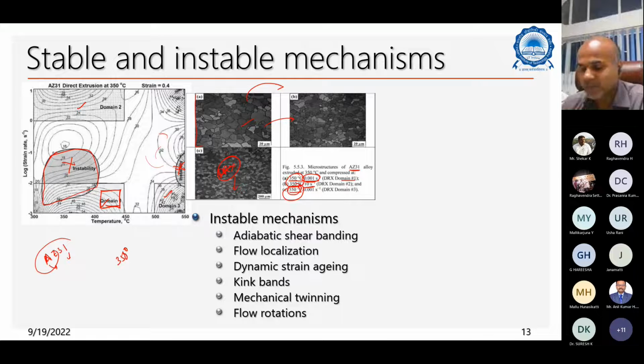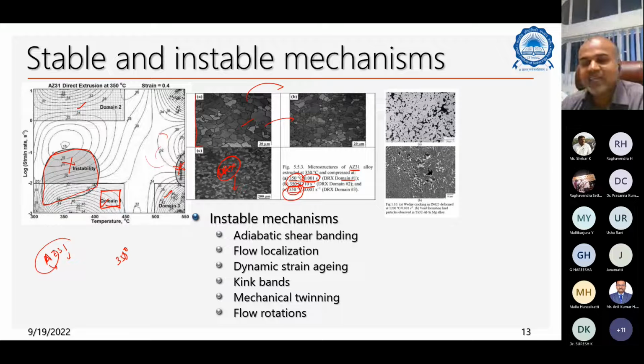Okay, so if you look at it here, for undesirable microstructure, let's say I've taken another material which I'm operating in this zone. What I get is a microstructure like this. The same material, if you are doing it in a good domain, a domain which is free from unstable regions, you get a very good microstructure. If you are talking about a domain which falls in the instability zone, you get a microstructure like this.